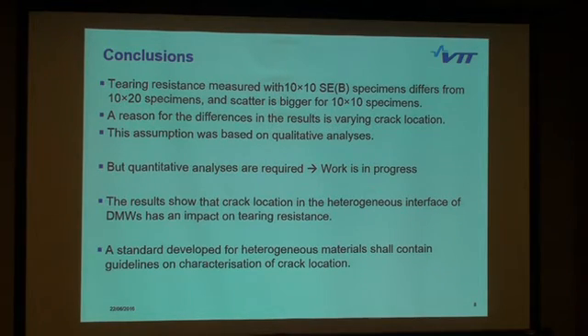And this is something that is really required. It's a systematic approach to quantify the crack location, because the fusion line might be wavy, and different researchers might define it in a different way, and they might also define the location of the crack maybe from the starter notch, or from the pre-fatigue crack tip, or maybe after 1 millimeter of crack growth. So we need guidance.